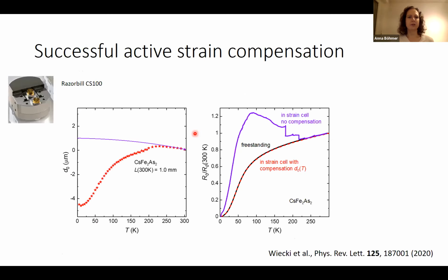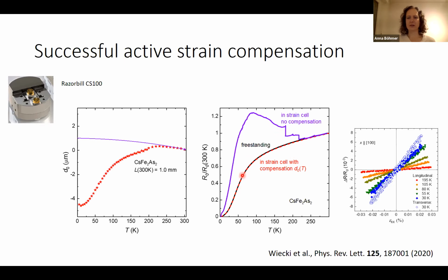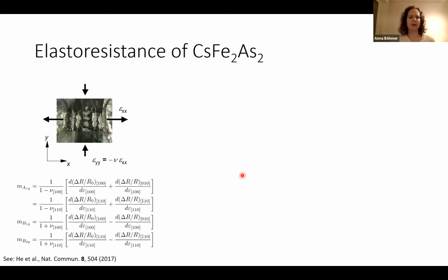And instead we use a Razorbill strain cell that was also just introduced to compensate for this strain mismatch. By moving the two sample mounts closer together on cooling, which would be these red stars here, we can keep a sample in a strain-free state within the system. We see that the resistance follows the one of a freestanding sample. If we don't do that, we break the sample or change the state dramatically. So once we have a sample, say at low temperature, in this state, we can then apply small strain sweeps and measure the elastoresistance. That's what we did again.